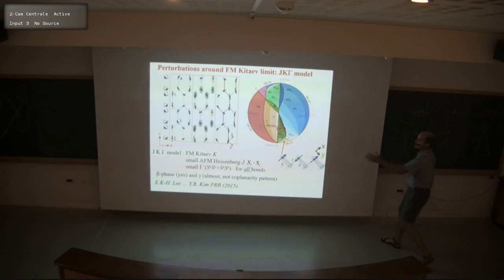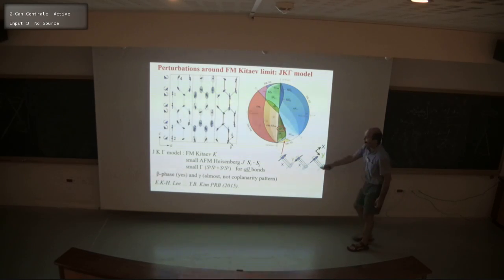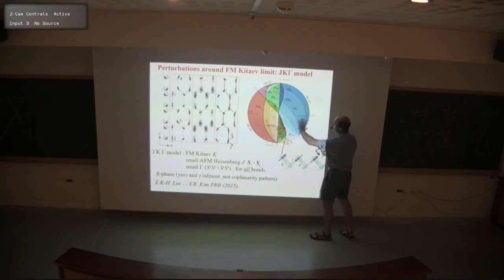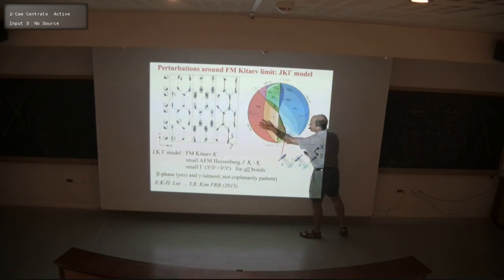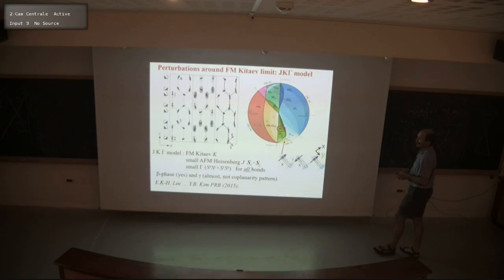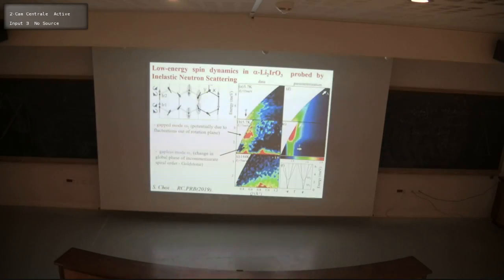So the zigzag chain is, of course, a cartoon, but one can generalize this picture to the full 3-dimensional lattice and use this so-called JKΓ model, and that produces a very complex phase diagram, but some of the key features seen experimentally with this counter rotation and so on are really explained by this minimal model. So what this shows is that the Kitaev interaction is the dominant exchange and does lead to magnetic structures that otherwise you cannot stabilize. So knowing the magnetic structure also gives us some insight into the magnetic excitations.